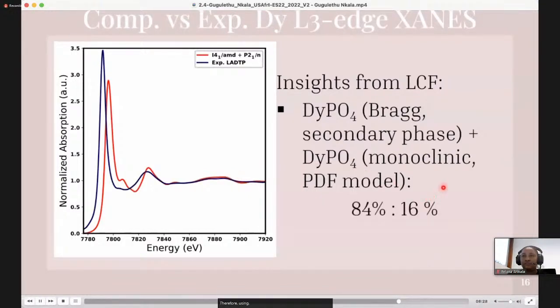Therefore, using linear combination fitting, we obtained the ratio of 84% from the tetragonal to 16% of the monoclinic dysprosium phosphate to get what we currently have as the best model describing what we observe experimentally, especially at high energy. Going forward, we seek to further improve on these computational calculations to then best match our experimental data as well as calculating the densities of states to understand the nature of our XANES spectrum, thus giving us information on more local influences of dysprosium doping on the structure of lithium titanium phosphate.